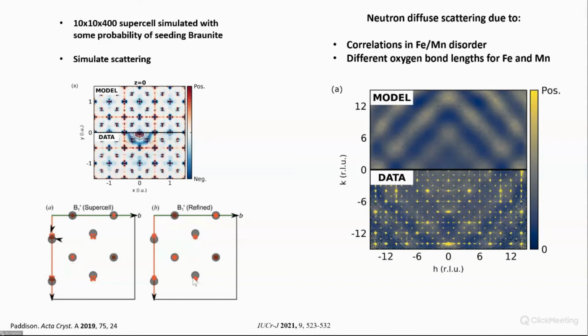Then how about the neutron diffuse scattering? Well, there it can either be correlations because there's some local ordering of the manganese and iron, or it can be because the oxygen bond lengths are different for iron and manganese. And it's the latter here, and I'll show you the model, but you can see the model we get out of this local order describes the diffuse scattering very well.